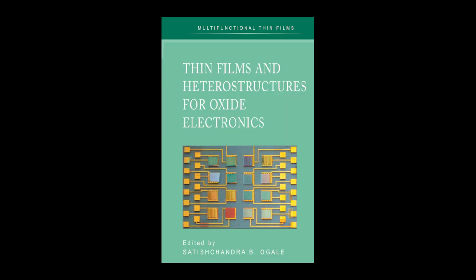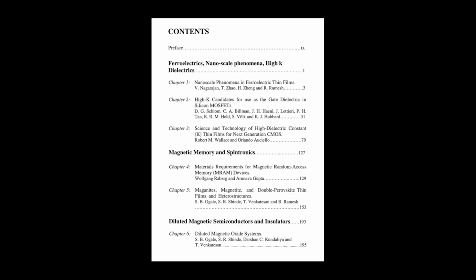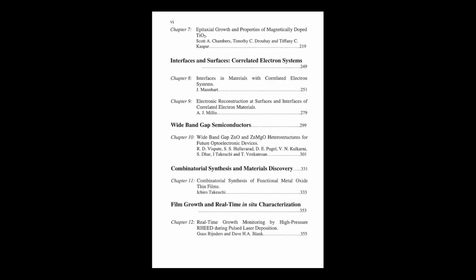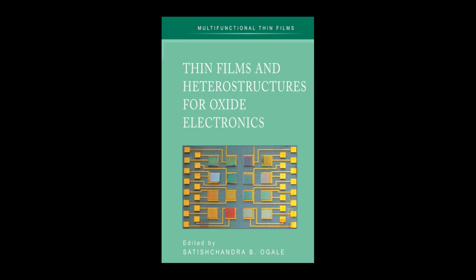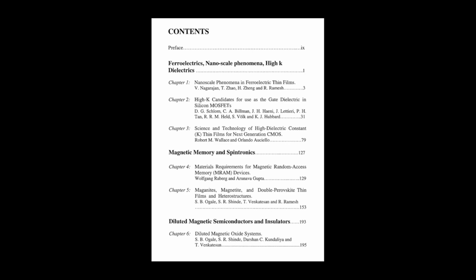Oh, it was absolutely an existential crisis for the industry. Your standard silicon dioxide, SiO2, has a dielectric constant K of just 3.9, fine for decades. But as transistors kept shrinking, the SiO2 layer had to get thinner and thinner. Below about 10 angstroms, that's literally just a few layers of atoms, the leakage current just exploded. Quantum tunneling. Electrons just punching right through the barrier. Exactly. Which means wasted power, way too much heat. Your chip basically melts or drains the battery instantly.